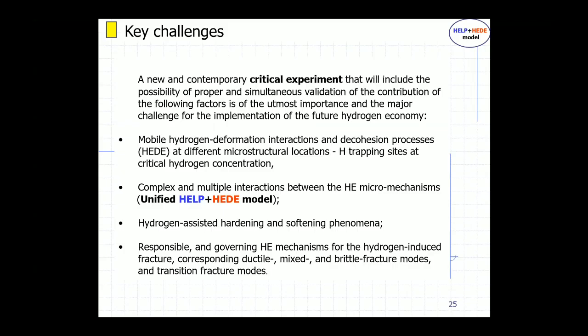And we must finally reveal probably the most enigmatic part, the hydrogen-provoked hardening and softening. So we can see hydrogen contributes to hardening and softening. And the transition between these two phenomena is strictly related to hydrogen embrittlement and complex hydrogen-material interaction, about which I don't have time to talk, and finally, the responsible and governing hydrogen embrittlement mechanism in different materials, including the advanced ones, with the corresponding ductile, mixed, and brittle fracture mode and transition fracture mode must be investigated, as I showed you.